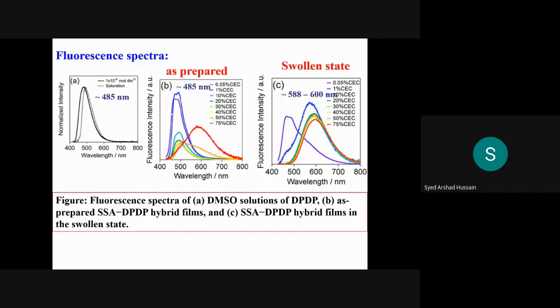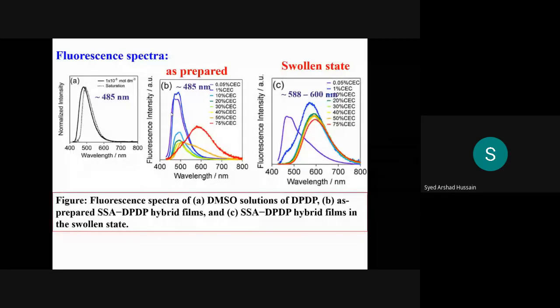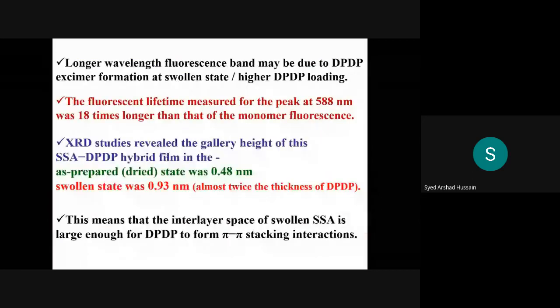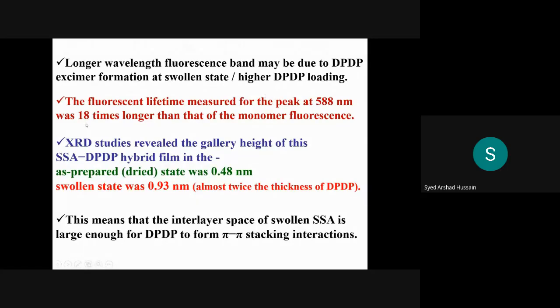Since absorption is a ground state phenomenon, you cannot see any change before and after exposure. But in fluorescence, you see the change after exposure. So we studied further to confirm this hypothesis. We measured the fluorescence lifetime for the original band and the band shifted after exposure, and we saw that the lifetime of the new band is 18 times longer than the original band. Again, this is the characteristic of the excimer, because it is a metastable system.